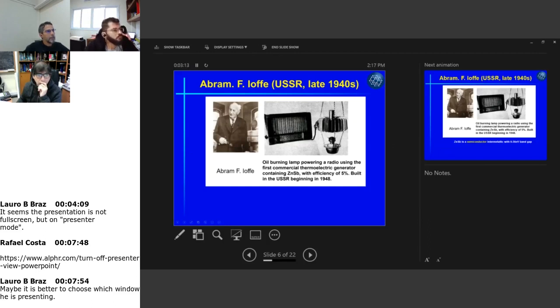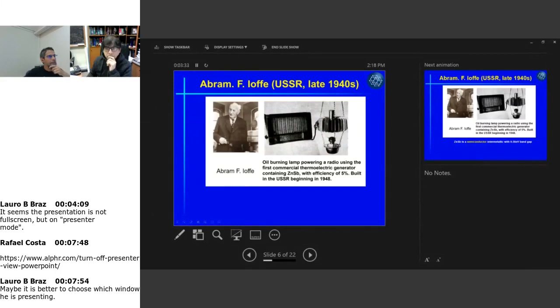And here we have an example of an oil-burning lamp powering a radio using the first commercial thermoelectric generator containing zinc antimonide. The efficiency of this device was very low, only 5%, but that was the beginning of the whole story. Well, not really. I can tell you a little bit about that soon. Zinc antimonide is a semiconductor intermetallic with a band gap of 0.56 electron volt.